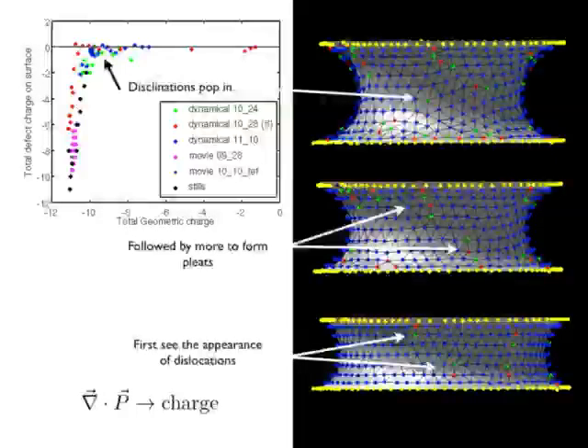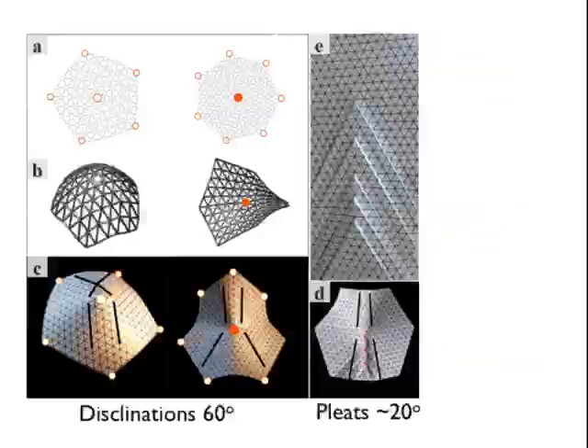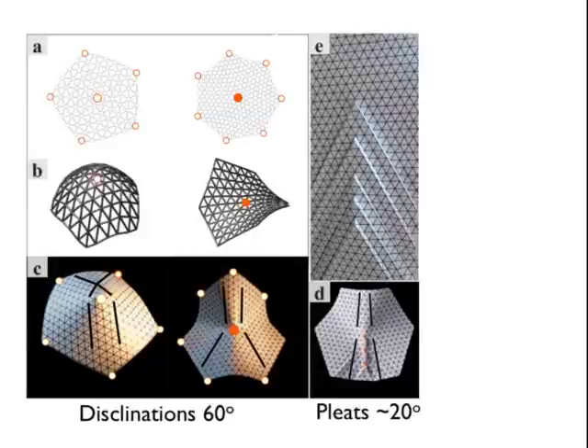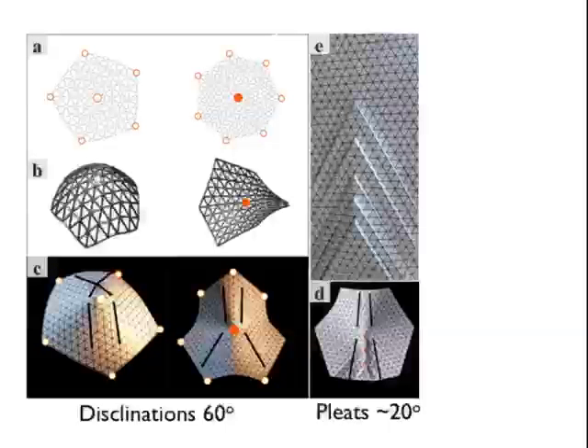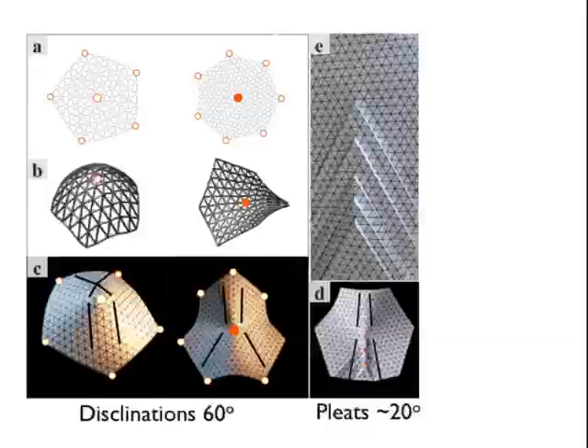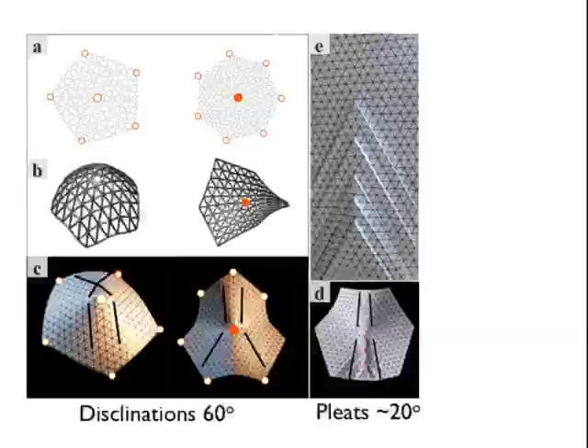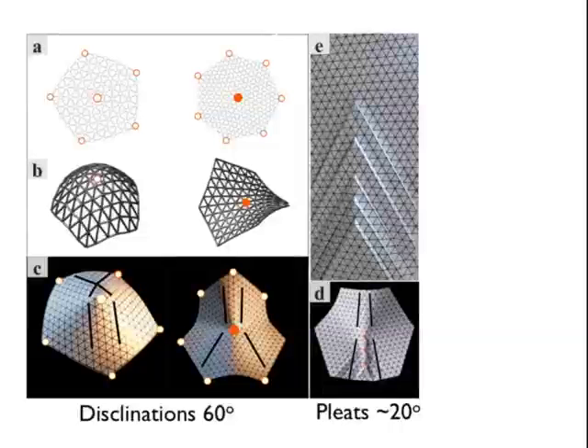so you can see how these things come in. One of the things that's interesting, I won't go through that, is this. So, if you add pleats, okay, it turns out if you have equally spaced pleats, what it'll give you is something which is a cone. I don't know whether that's obvious to everyone. It'll give you something that's a cone because you're adding material constantly as you go down. If you're adding material constantly as you go down, that's just what a cone does, right? And a cone like that doesn't have any Gaussian curvature. That's what I was trying to convince you of before, okay?